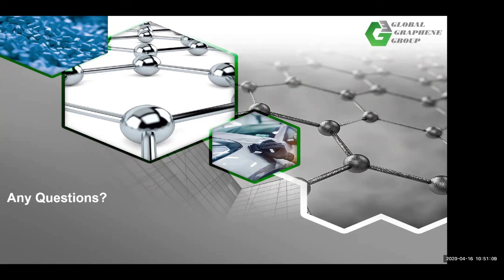So that's one point. The second point is, in terms of anti-corrosion, we have a lot of experience with that, specifically referring to metal-rich coatings and also polymeric coatings. On metal-rich coatings, let me speak on behalf of that real quick. A commercial metal-rich epoxy primer is about 70 to 90% zinc dust. It offers very good corrosion resistance and very good mechanical strength. However, over time, the mechanical strength and adhesion tend to decrease.